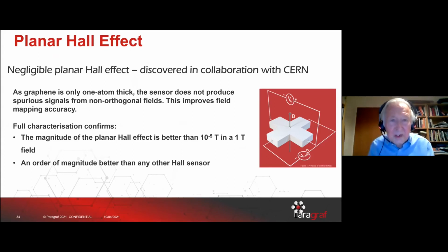Graphene is the thinnest material in the world. It's just one atom thick, carbon atoms, and the planar Hall effect is negligible. Full characterization by CERN confirms the magnitude of the planar Hall effect is better than 10 to the -5 Tesla in a 1 Tesla field. So an order of magnitude better than any other Hall sensor.